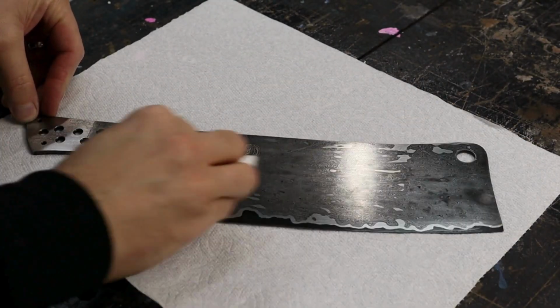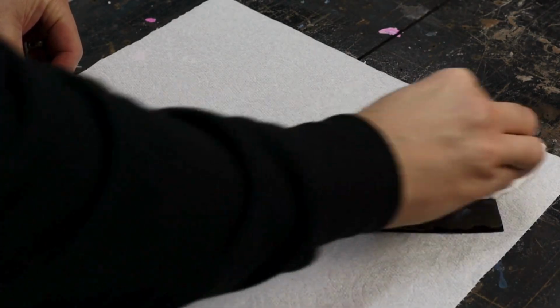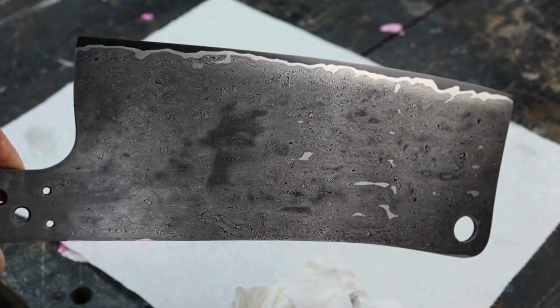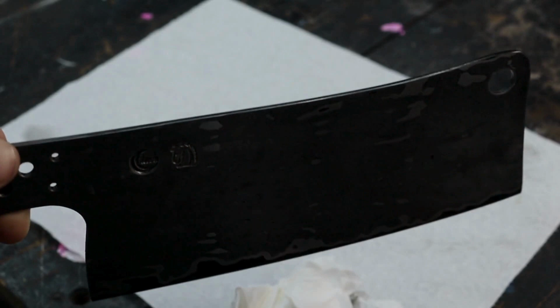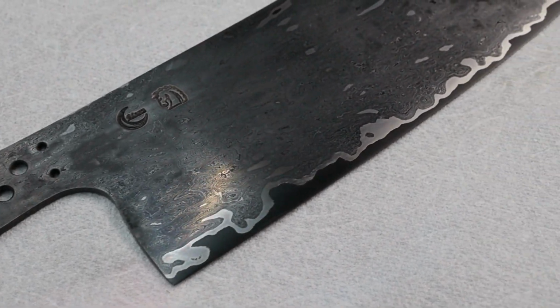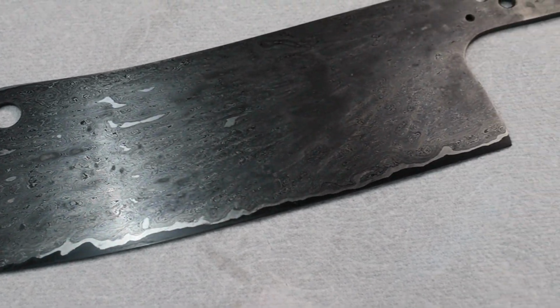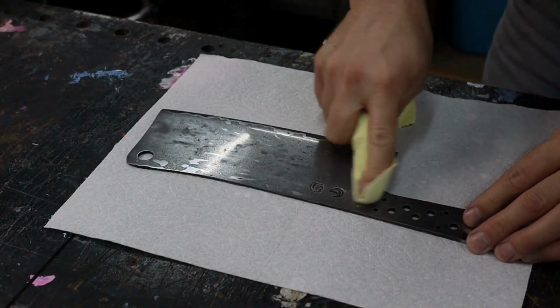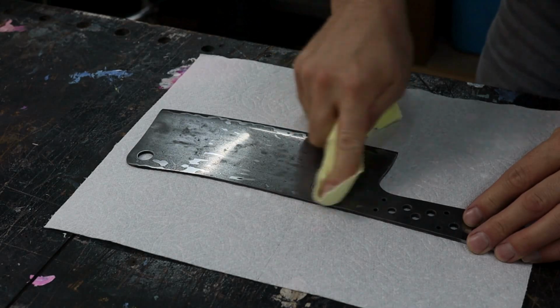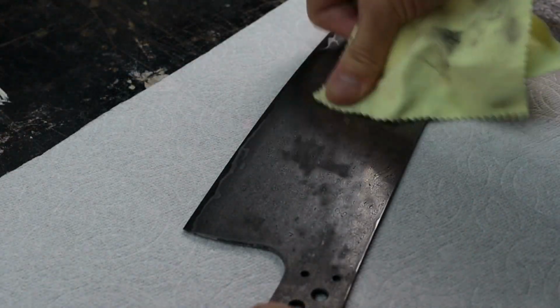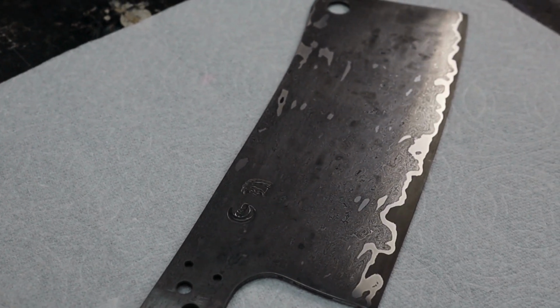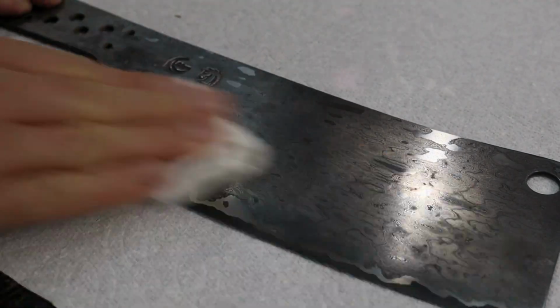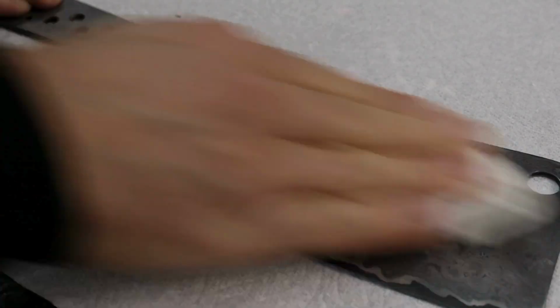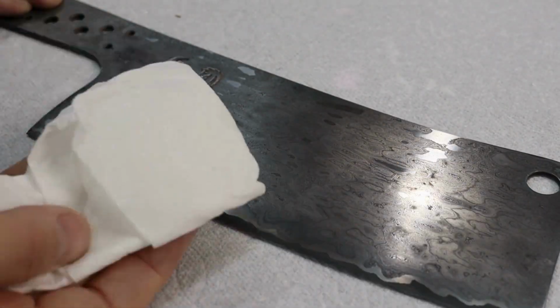The next morning I wiped off all of the WD-40 and then washed the whole blade in warm soapy water. I touched up any areas where the 15N20 looked a little yellow or dull with the sunshine cloth. You can see that once the oxides are set, they shouldn't rub off at all when you wipe the blade. You don't see any black residue on the paper towel.